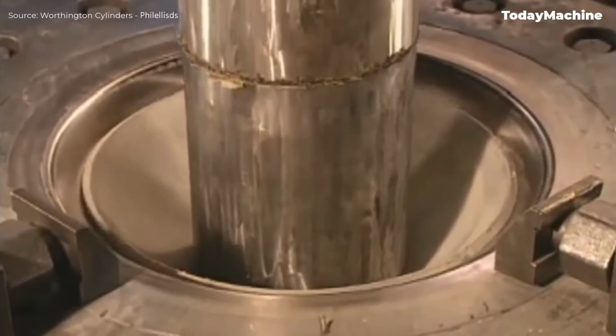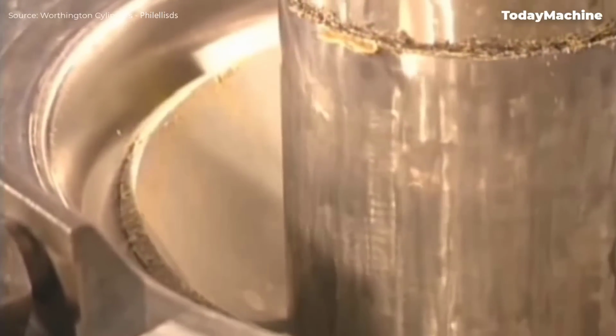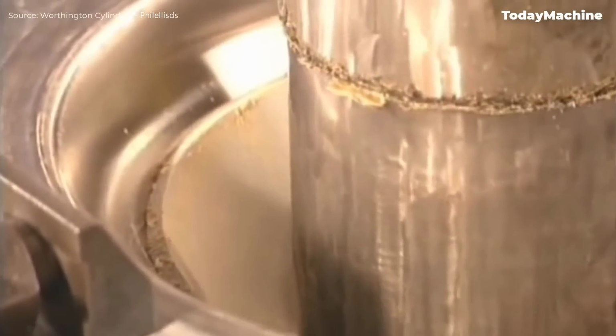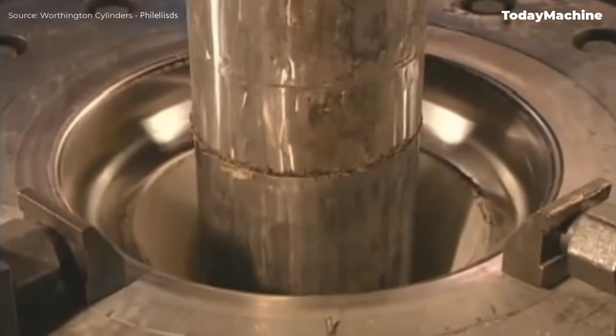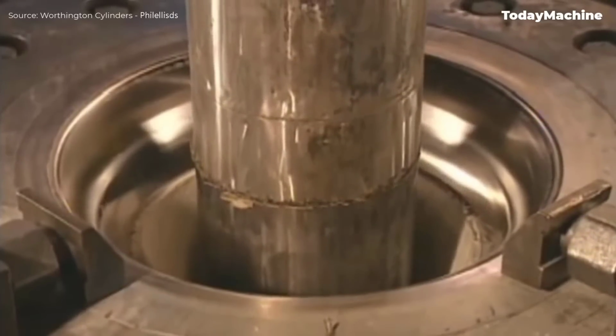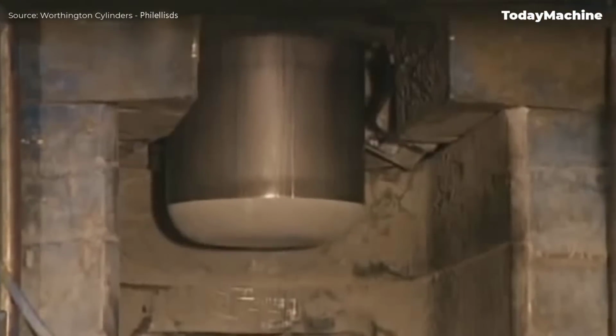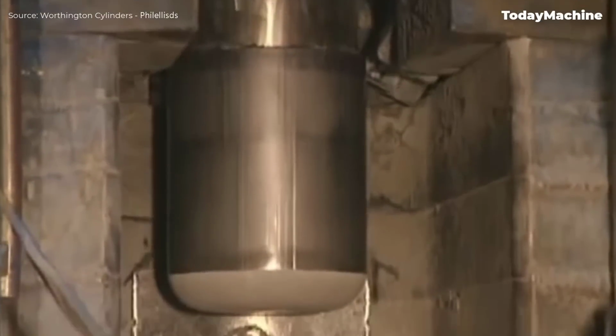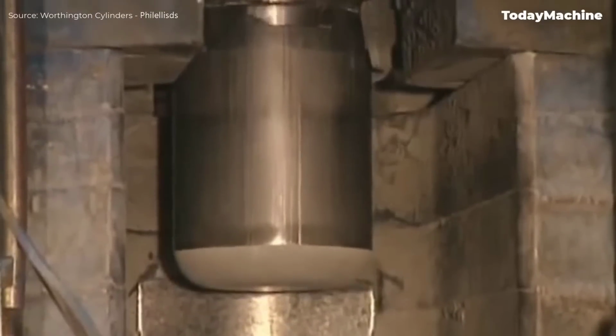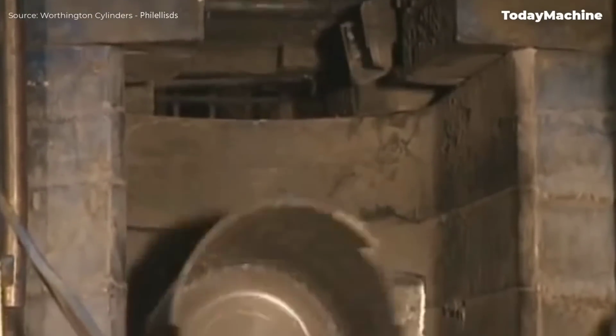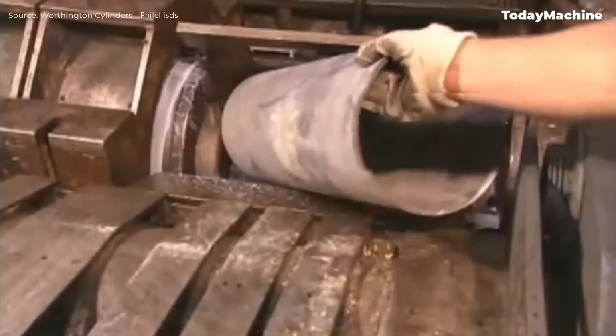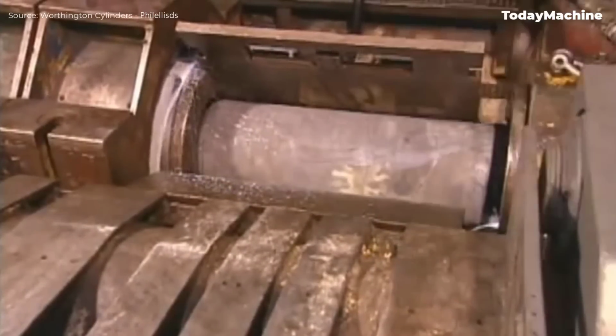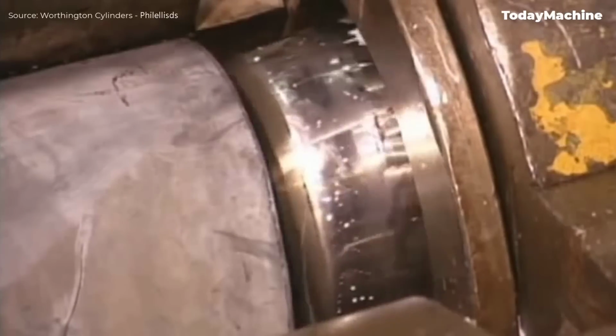After each draw, the cup is stripped from the mandrel using stripper jaws. The cups are then subjected to annealing, cleaning, and re-lubrication before undergoing additional draws. The final draw, often requiring up to 250 tons of force, refines the cylinder's shape. Since draw rates are relatively quick, a flood-type coolant is used to prevent overheating during this stage.